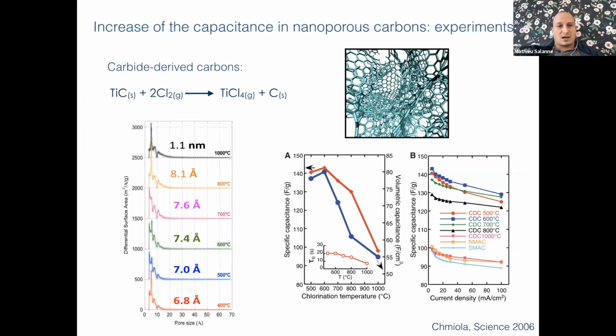And by using this kind of very microporous carbon, they show that the capacitance can change by a factor 2. So this is a very large difference. And in fact, you have very strong confinement effects in these devices. So we have 2 important effects to take into account. It's large concentration of ions and the nanoporosity of the device.